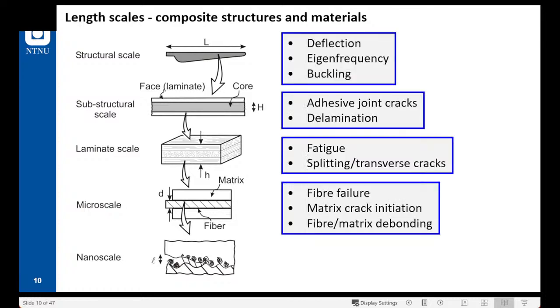At different scales, we have different damage modes. I will not go through all the list, but at the structural scale, we can have deflection or buckling. At the component level, we can have delamination between the skin and the core. At the laminate level, we can have fatigue or transverse cracks. At the micro scale, we can have fiber failure or matrix crack or fiber matrix debonding.